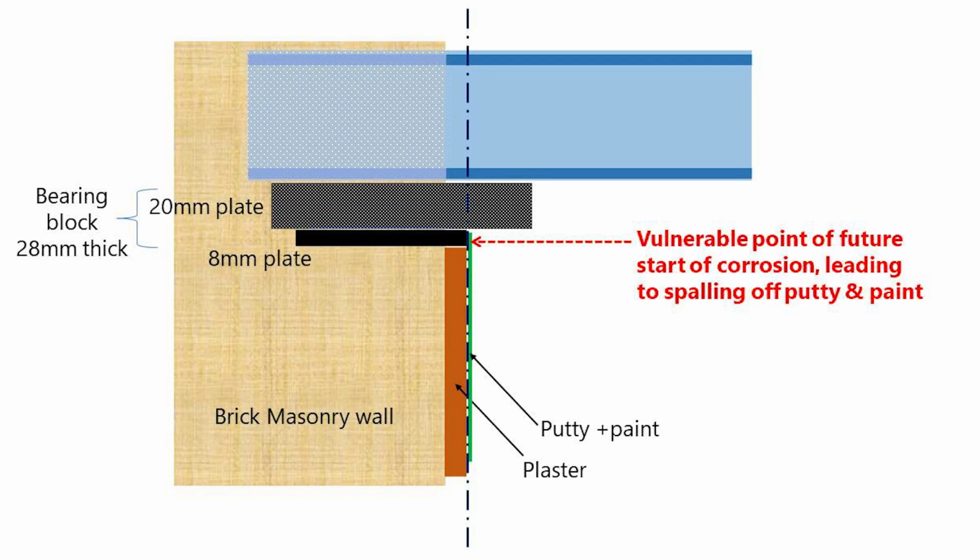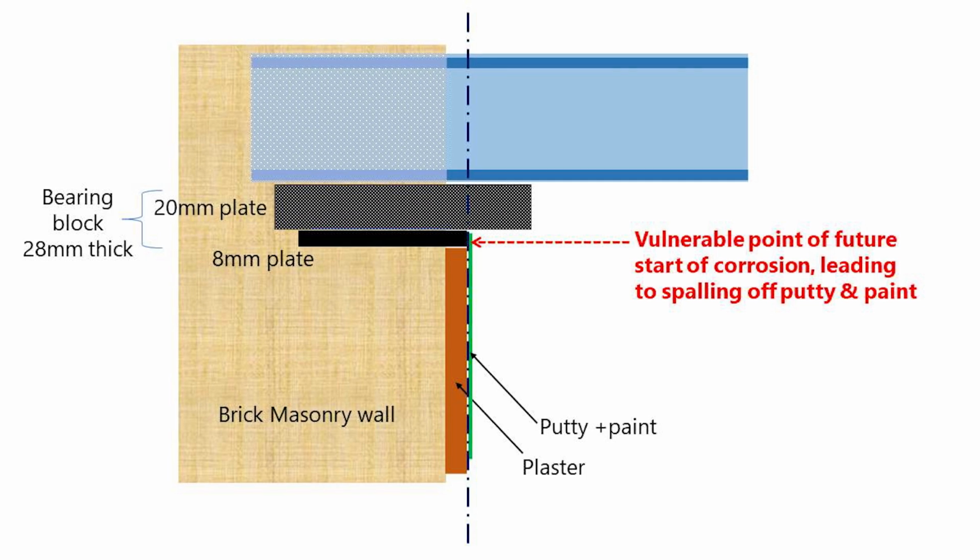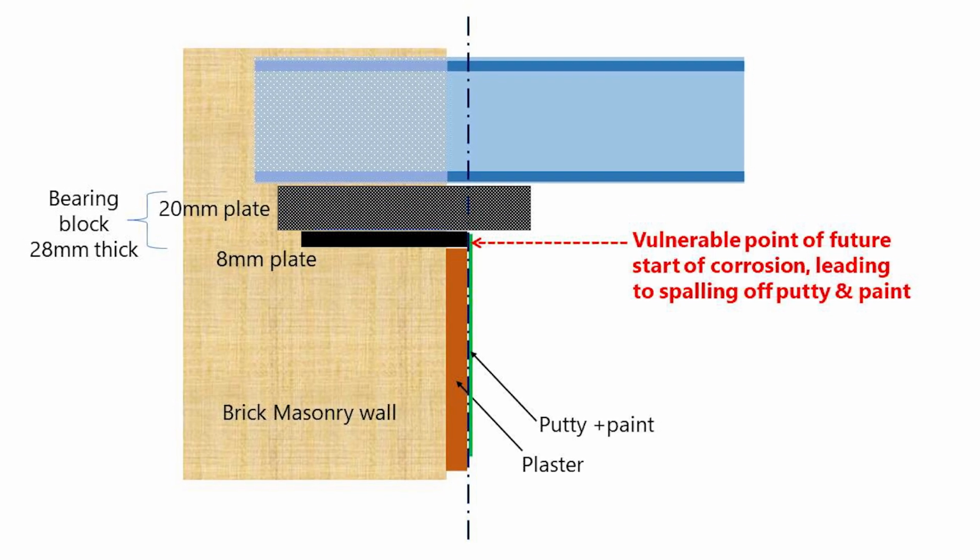It will expand in volume and make the surface paint spall off from the surface locally, and putty will show fine cracks on the wall surface. It will give an indication that corrosion has started. Immediately, preventive maintenance can be initiated. I think this simple improvisation on traditional method can bring proactiveness from maintenance point of view.